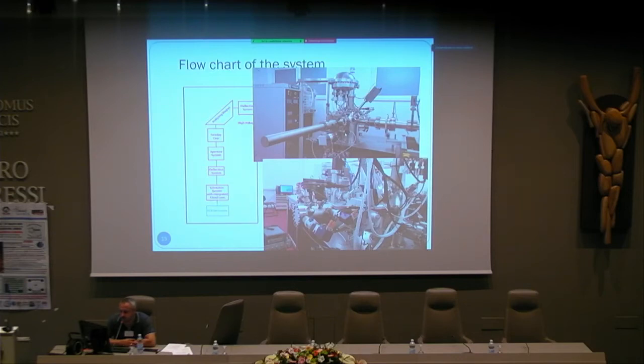We have all kinds of diagnostics. We have a residual gas analyzer for the purposes of measuring the vacuum quality. We also have an electron detector, which allows us to do Auger spectroscopy, so we can reliably measure the contamination on our target.